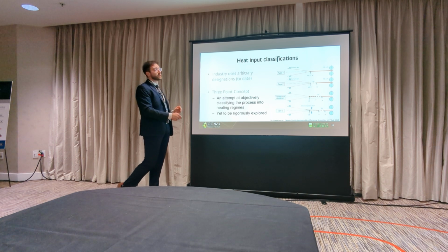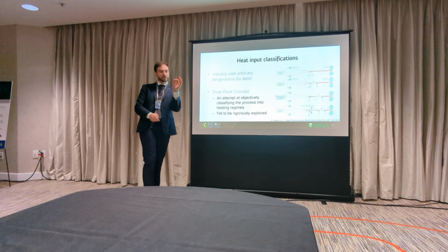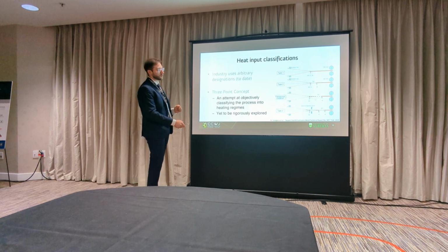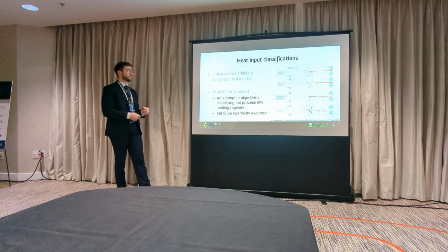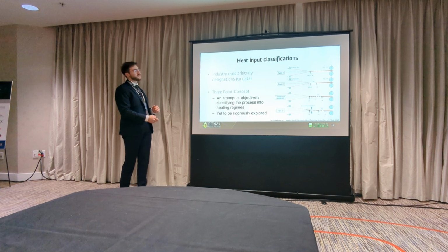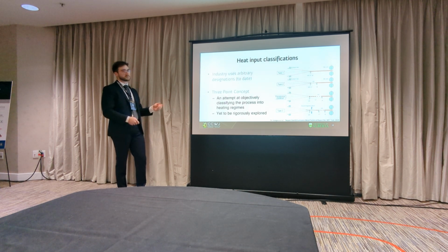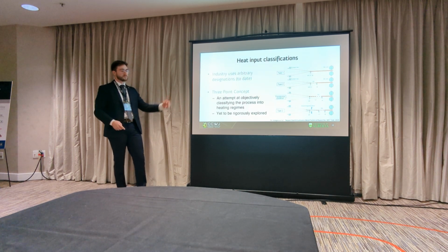When you're in the low heat input condition, they do share the same point in space. As you increase power to the V, your weld point starts to shift downstream. And then as you increase heat input further, your geometrical apex point, your point of first contact, which would be that arcing point that I mentioned earlier, and your weld point, they all are separate at excessively high heat inputs. This concept has been presented as an attempt to objectively classify the process, but it's yet to be rigorously explored.